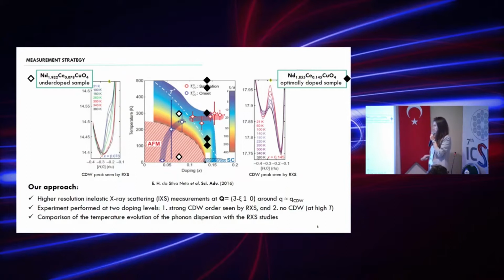However, the situation is different for optimally doped samples, because here the charge order peak is not visible, so we have only a background visible here and a little bit of this peak at low temperatures. So we have two different regimes for charge density wave order. Our approach was to compare the evolution of phonon dispersion for these two different samples. We also explored different temperatures because we see that charge density wave order is a highly temperature-dependent phenomenon.